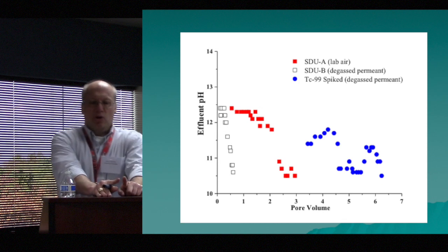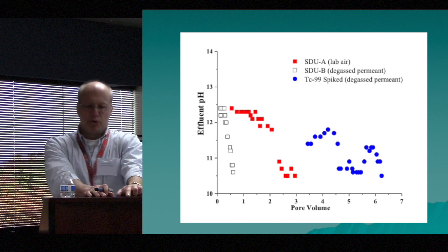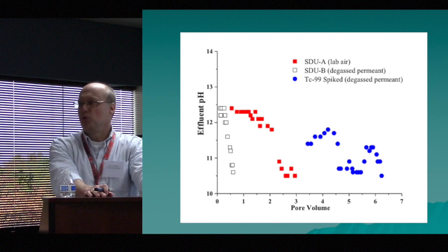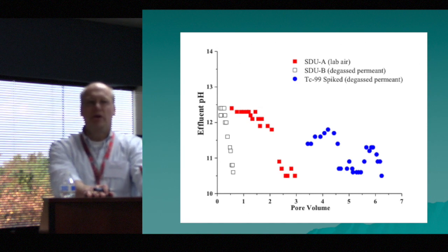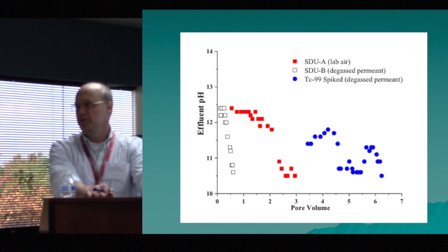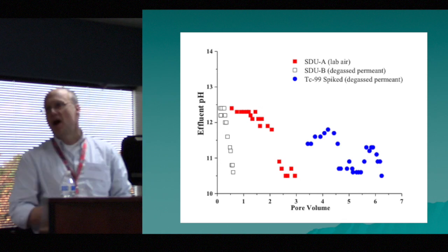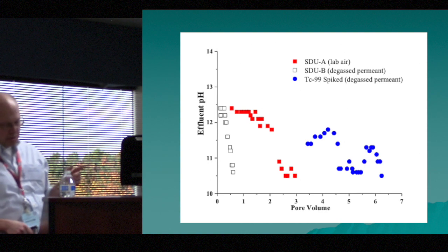Here's the problem. We started out trying to use flow-through cells, and the actual flow rates were so low that they were completely useless. The other thing is, if you're collecting 1 or 2 mils a day and it has to sit on the counter, the pH of those samples went down by about 1 to 2 units before you could ever measure it. And so there's a lot of potential error in these measurements, especially with respect to pH.